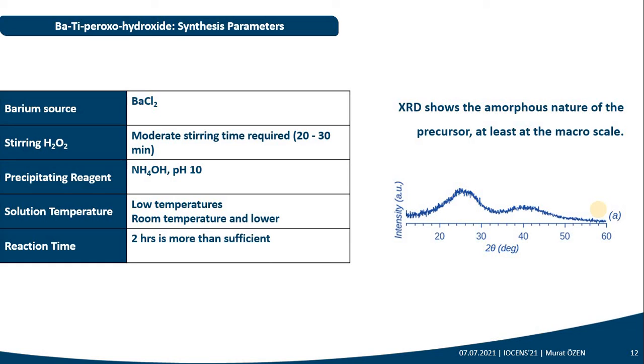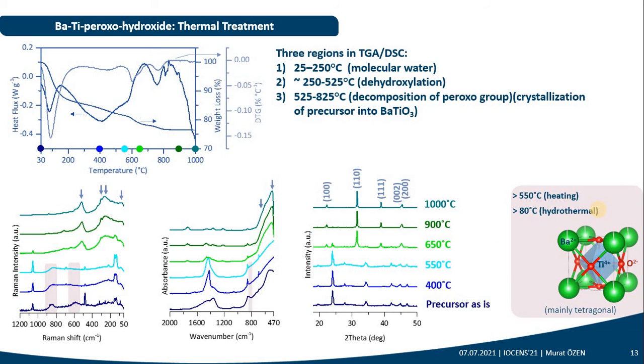An XRD result is shown here, which shows a very broad band and is typical of amorphous precursor materials, at least at the macro scale. At the nanoscale, the material might have some structure behind it, but all in all, we see that the precursor material that was obtained here is an amorphous material.